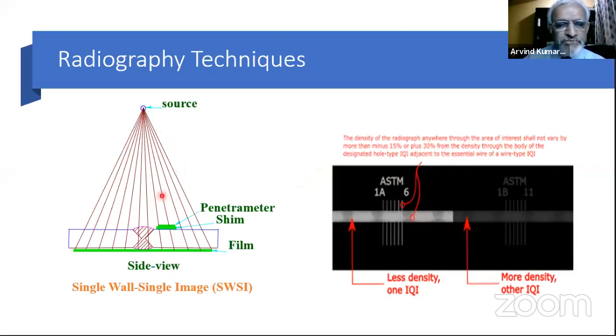So we have one simple technique where if you're carrying out radiography on a plate, like a hull plate, which is long, and you have to do X-ray of that, then you have to use the technique which is called single wall, single image. Single wall means the radiation is penetrating through one wall, and what you're getting is one image. So that's why we call it single wall, single image. And this is the kind of thing that you will see on the radiograph.